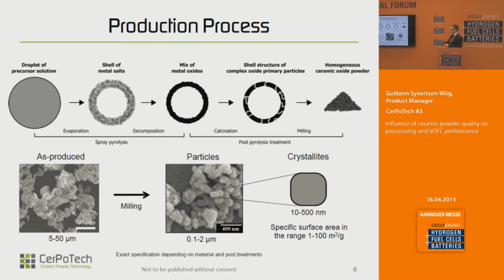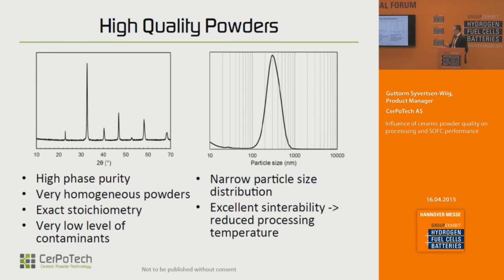And due to the evaporation of the water, you naturally have these hollow spheres that need to be ground down. On the bottom left, you can see an example of how these spheres look, because this is also something we can tune, the size of these and the thickness of the shell and so on. And then we mill it down, and in the middle down here you can see the typical particle size of these powders. The crystallite size can vary from 10 to several hundreds of nanometers, and the particle size is typically sub-micron, a few hundred nanometers. This also depends very much on which material we're talking about, because thermodynamics is playing a major role here. And we can also modify the temperature and time we're using to optimize the properties.